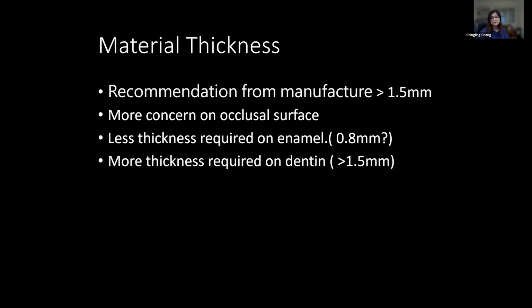The material thickness is usually recommended to be higher than 1.5 millimeters, but it's more of a concern on the occlusal surface. So when you're just doing a veneer, it doesn't involve the occlusal surface, and you can have less reduction on the non-occlusal surface. When you bond the porcelain on enamel, you actually have less thickness requirements. But if you bond on dentin, you definitely need more thickness. It's recommended to be higher than 1.5 millimeters.